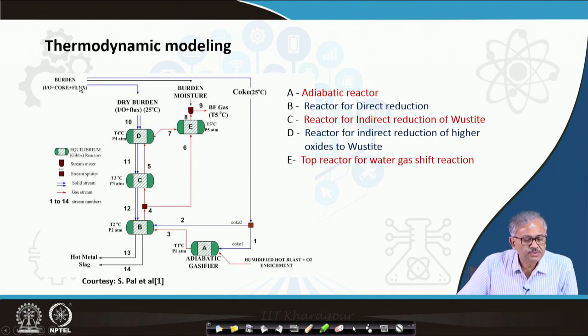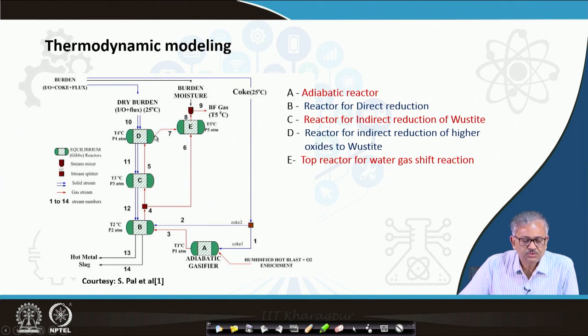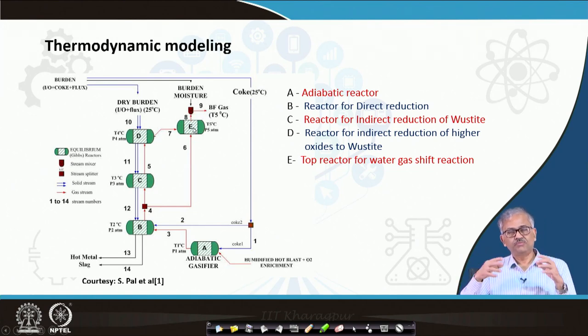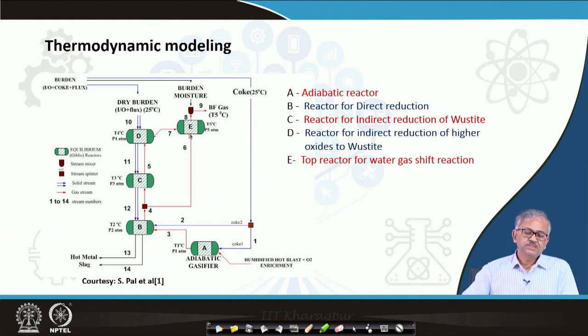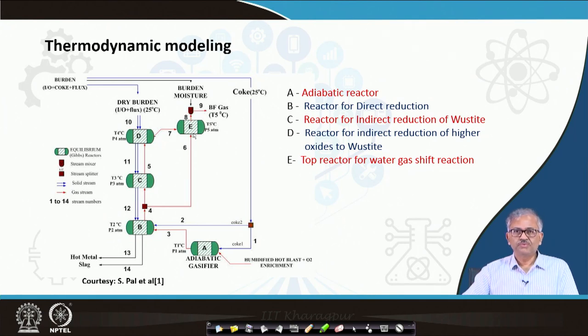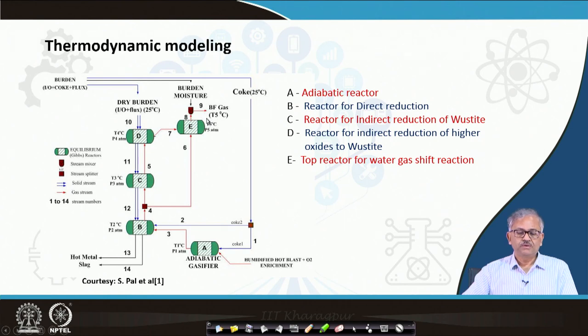From the burden, we have taken out the moisture. You can find there is a moisture stream and a mixture. The CO bypass gas, the equilibrium CO/CO₂ mixture from reactor D, and the burden moisture will all be mixed together in reactor E and come to thermodynamic equilibrium. This reactor E is basically for the water-gas shift reaction — CO may react with moisture forming CO₂ and H₂. Finally, you will get the blast furnace gas composition out of this reactor.